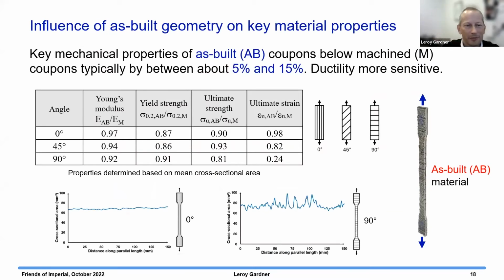What I've got here is a series of numbers in this table, which are the ratio of the as-built mechanical properties to the machined mechanical properties in order to reveal the detrimental effect of the surface roughness. And you can see for most of the properties, so the Young's modulus and the yield strength, for example, you have around about a 10% reduction in strength and stiffness as a result of the surface undulations.